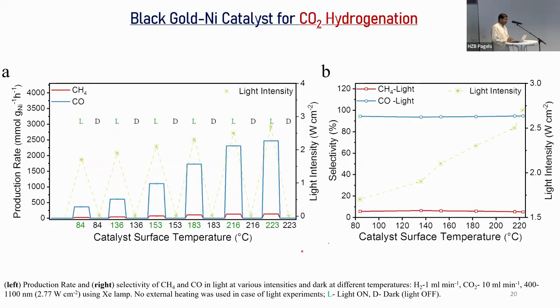So the first thing that we did is we tried to understand the effect of light intensity on the productivity, and what we see is that with increasing the light intensity from say 0 to 3 watt per centimeter square, you see an increase in the productivity of CO. Now when you look at this particular number, say 2.77 watt per centimeter square, L is light and D is dark. Look at the number here, 2500 millimole per gram per hour. It was 1.75 micromole per gram per hour, and suddenly it changes. It's a dramatic change, not only in number but in the unit, from micromole to millimole, by simply tuning the catalyst design. So that means electrons were not recombining, which you were able to resolve by creating this black gold nickel system.